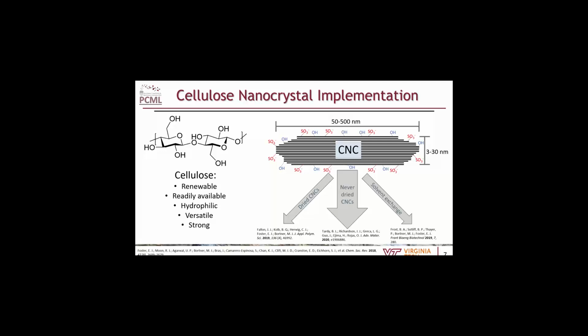So what I use is never-dried CNCs, where I just order a batch of CNCs from either a collaborator or University of Maine or a similar supplier, and they just send it to me where they've done all the rinsing, they've concentrated it down to 12 weight percent in my case, and from there I can dilute it with more distilled water, etc., and manipulate the concentration that way. I keep them in this aqueous suspension and test that on instruments such as the VROC, which I'll get into a bit more, because I want to see what the high shear rates and some temperature changes will do to just pure cellulose nanocrystals, since I want to keep my system as simple as possible—I just want to look at the CNCs.